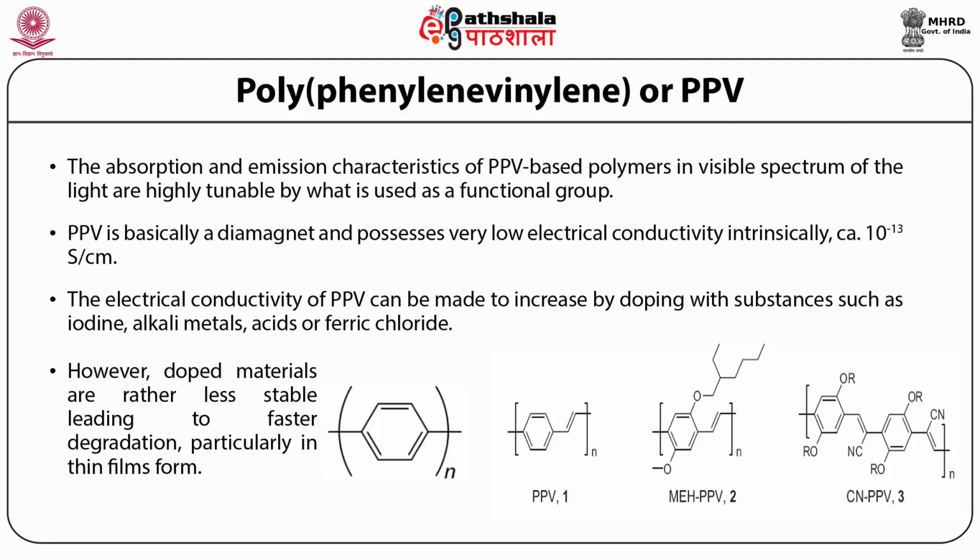Higher conductivities can be expected in the alkoxy-substituted PPVs, which are generally easier to oxidize than the parent PPV. The longer the side chains are, the lower the conductivity, as it is very difficult for charge carriers to hop between chains. PPV is the only polymer of the rigid rod family that can be processed into a highly ordered crystalline thin film.